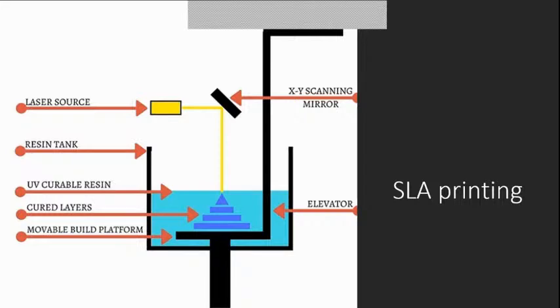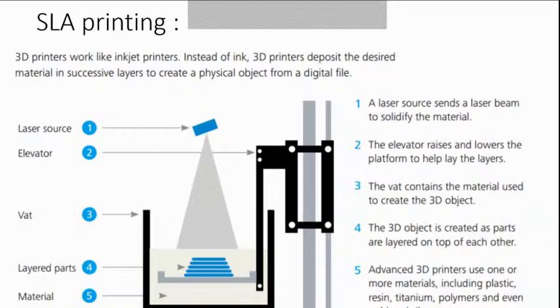So there are different stages through which the printing happens, and as you can see at stage 4, the part is getting manufactured layer by layer, and the material is kept in the tank, or it's also called the vat. Okay, and if you look at part number 2, it takes the part up or down to make the next layer. So if it's taking it down, we print it straightaway. If it's taking it up, we print it inverted. The part is inverted.